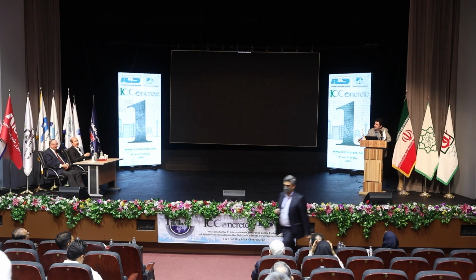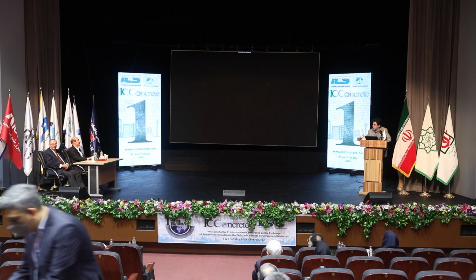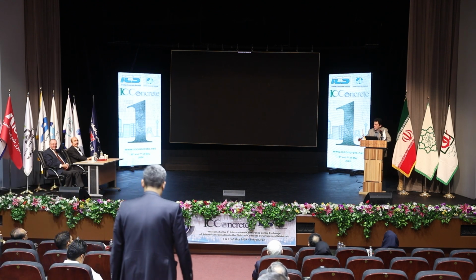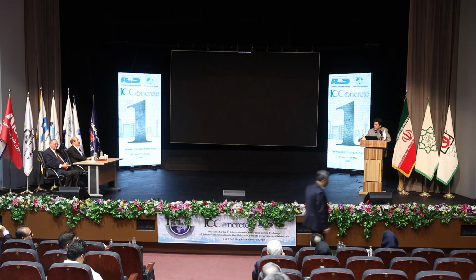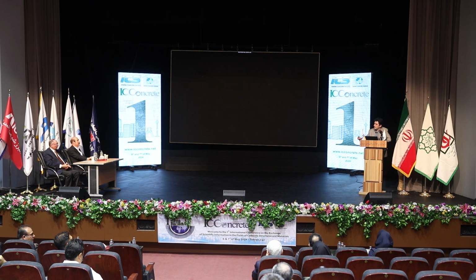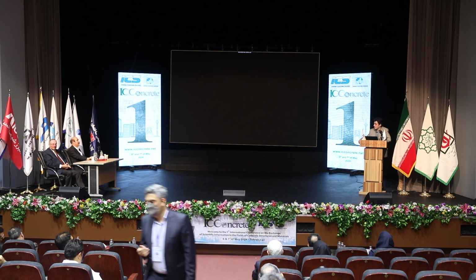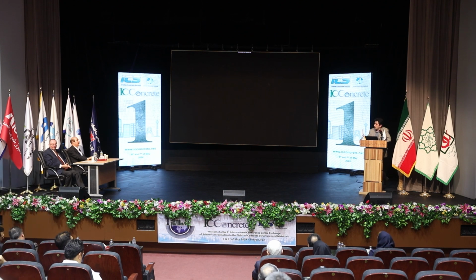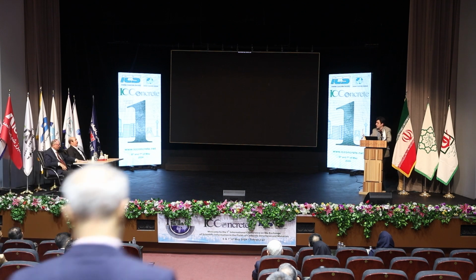Yes, actually there's no limitation in our formulation. It is extended to any structural member, and there's no limitation in the basis of our formulation and the results. You can see that we have solved this slab, which can be a structural member, and we are going to extend this to different defects in structural composite structures, which is very relevant in structural analysis, such as the debonding of these CFRP composites from reinforced concrete beams, for example, in harsh environments. We are going to extend these formulations for the case of defects and damage, including debonding conditions and different damage evolution.